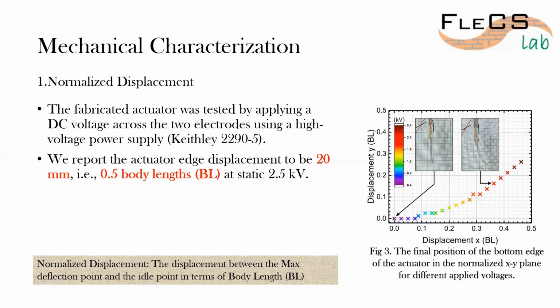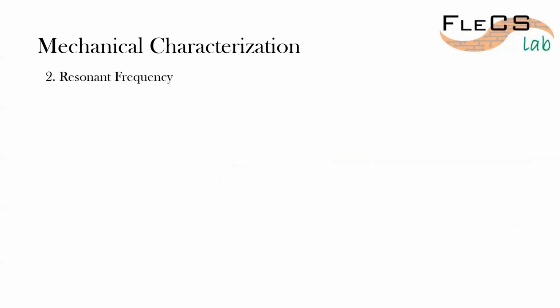And after that, typically it breaks down. We saw breakdowns of the order of 3 kilovolts for this particular thickness of the elastomer. So once we are able to do that, we are able to get a specific static displacement. We basically wanted to see what kind of dynamic characteristics, or response, we get from this actuator.